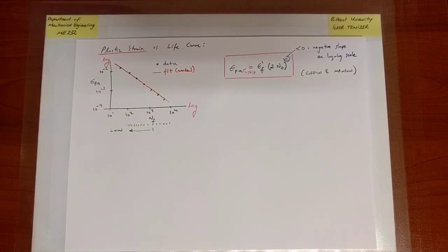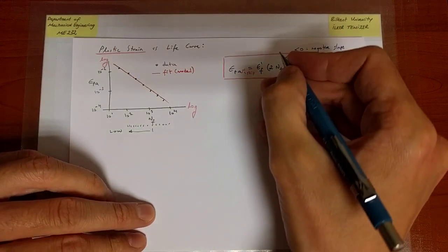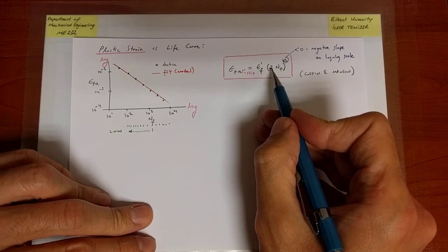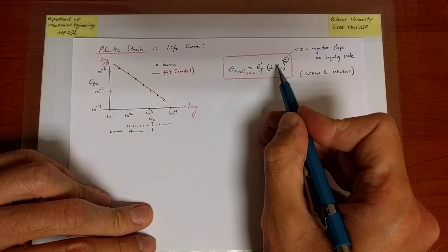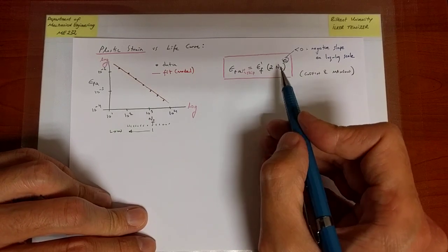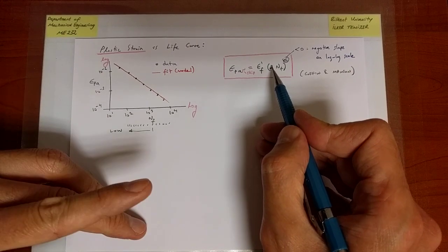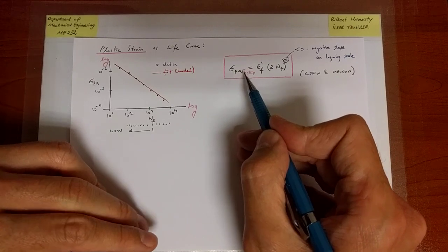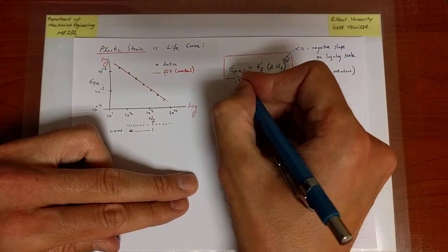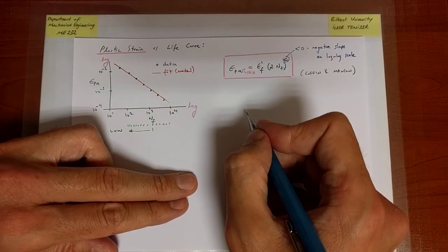Okay, now at this point you may, however, remember also the Basquin equation argument. In the Basquin equation, we had said, well, why do we have a factor of 2 here? Because 2N_f is the number of load reversals. And if failure occurs at the first load reversal, I put a 1 there, and so this thing becomes 1. Failure occurs at epsilon_PA equal to epsilon'_f.